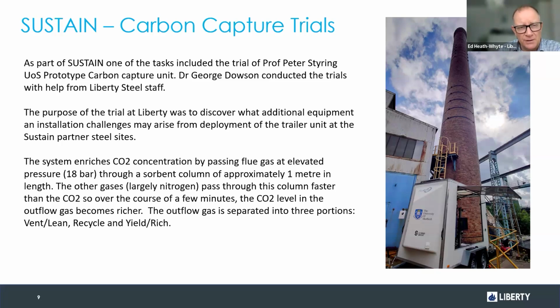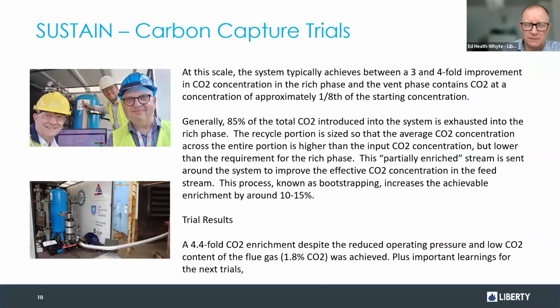We did find that the actual CO2 content was quite low in that stack. That's possibly due to air ingress between the stack and the furnace, but it was only about maximum 2% CO2. However, they managed to capture that and also managed to concentrate that CO2 up to about 8%. So that was a successful trial of their process.